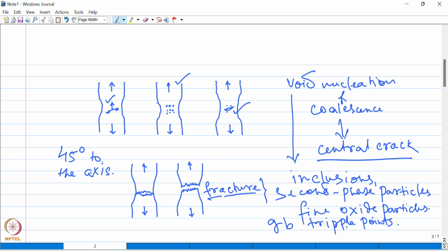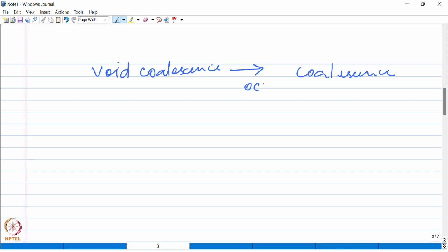And this coalescence occurs by elongation of the voids and elongation of the bridges of the material between the voids. So looking at the finer details of this void nucleation and coalescence, we can say that the coalescence occurs by elongation of the voids and the bridges of material between the voids.